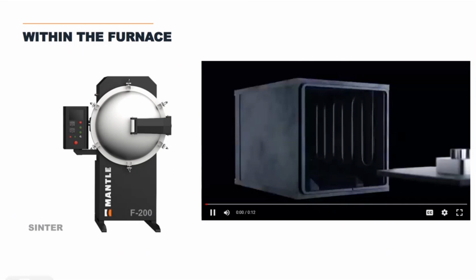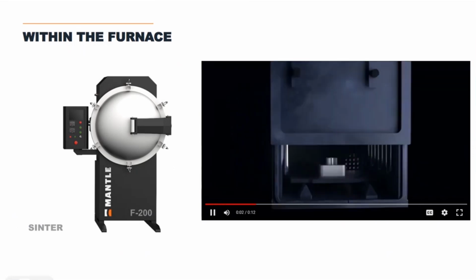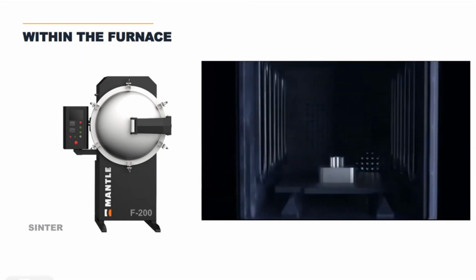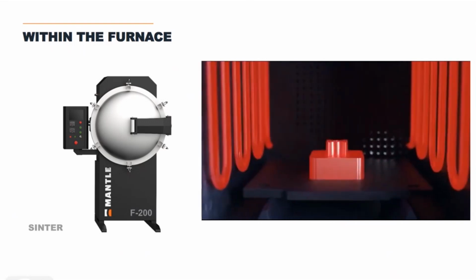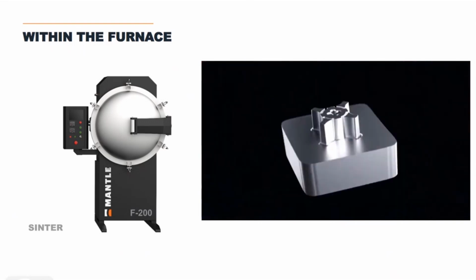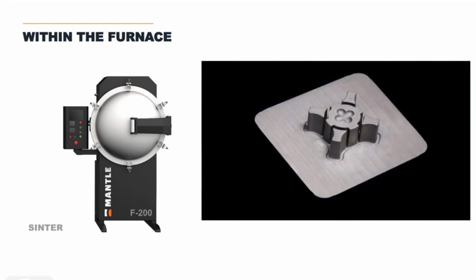Inside of the furnace, it's a little harder to get a camera inside of a high temperature furnace, but essentially this is a big oven under controlled vacuum and some gas to control the atmosphere that sinters the part into a dense metal part after.